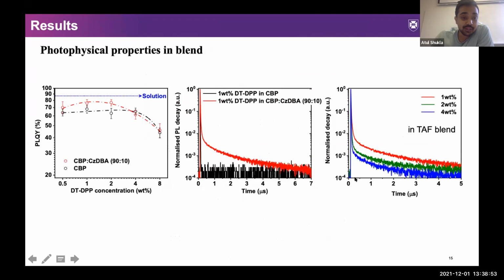The host matrices that we used were just CBP host for comparison, and the TADF host for the main work. So this figure shows the PLQY as a function of DPP doping ratios. As we see, at lower doping ratios we get higher PLQY from the TADF assisted blend. This is majorly because of better energy transfer, and some contribution also comes from the recycling of triplet excitons. But when we go to higher concentration, we find that it's very much comparable to the normal CBP host. That is because the Dexter energy transfer becomes more prominent at higher doping ratios, which leads to a reduction in PLQY.